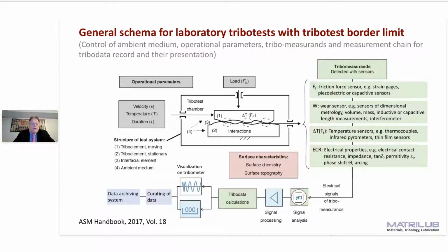by means of a friction sensor of any type, the friction force. You can measure the wear of both elements, or of one element, by different techniques. Same for the temperature and also electrical properties like contact resistance, impedance, phase shift, permittivity, tangent delta, arcing, and so on. At the end of the test, you can use these specimens for surface analysis in order to see where the changes are. At the end of the day, all those measurements today are electrical or digital ones.